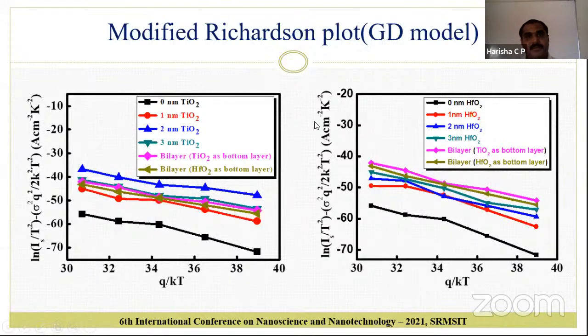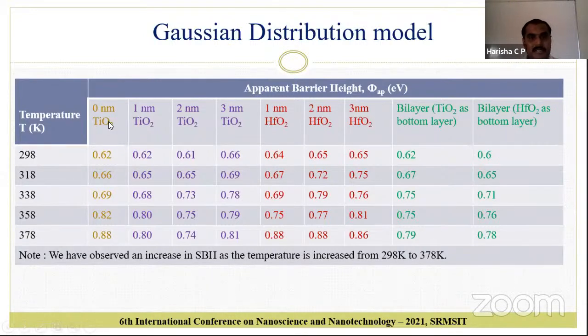So in the thermionic emission model, we have seen a conventional Richardson plot. Here in the Gaussian distribution model, we have seen a modified Richardson plot. This is a linear graph you can see here, but the conventional Richardson plots have shown non-linear behavior. So this clearly indicates that there is an inhomogeneity. What is the other confirmation for inhomogeneity? As the temperature increases from 298 to 378, there is also an increase in Schottky barrier height in all the models, in all the contact structures.